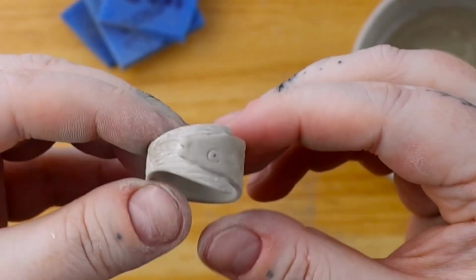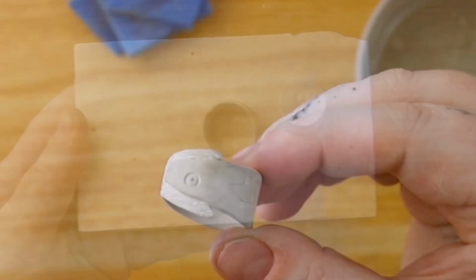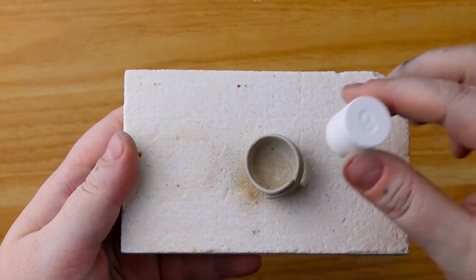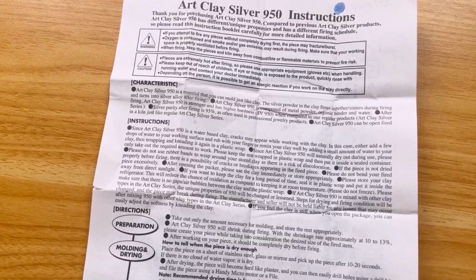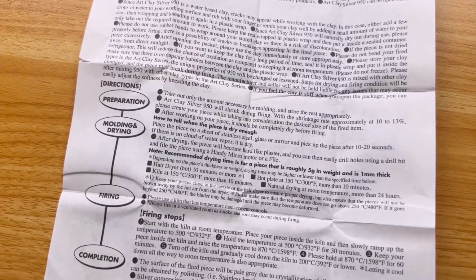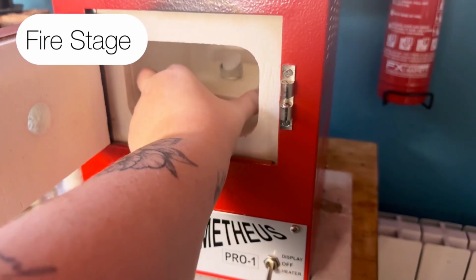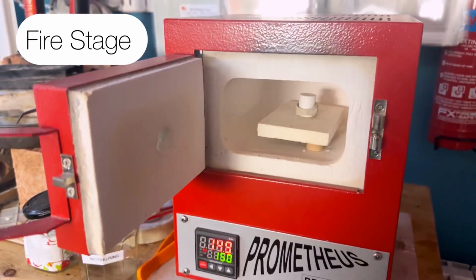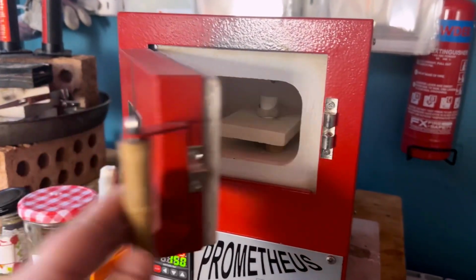Now I'm choosing my fireable pellet. I want my final size to be a UK P, which in this instance is a US 8. The instructions on how to fire your Art Clay silver in your kiln are in the bag. I pop my clay in cold. I then ramp up my kiln to 500 and hold for 30 minutes.